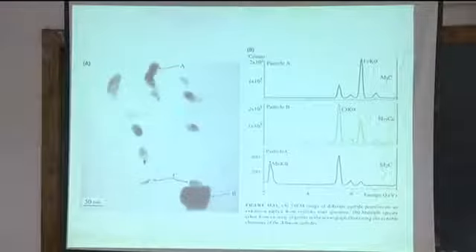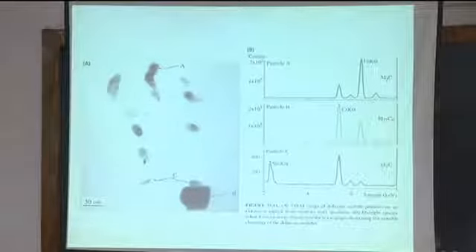If you take this and see, many of these are less than 50 nanometer particles. Now, with the TEM, you can just take EDS analysis from selected regions. This is the whole spectra. So that way you can take from a 20 nanometer, or a little bigger particle, that area you can take an EDS analysis.